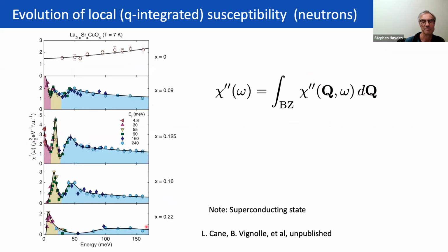The problem more is that maybe we may not have captured everything here. But I think at the higher energies, where things are not dispersing very much, the neutrons may not be picking up some of the weight, because you have to have contrast to see the signal in neutrons, whereas with X-rays you can directly see it. So this part up here probably is underestimated with the neutrons. That is true. But this part here at the low energies, I think, is clearly changing with the neutrons.